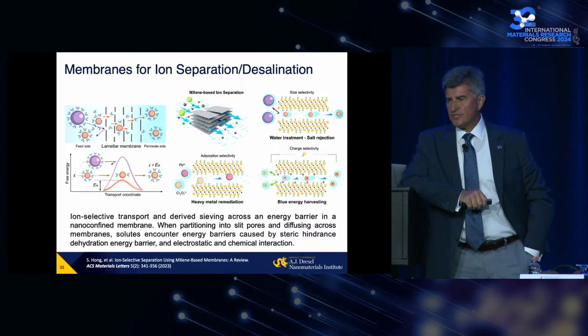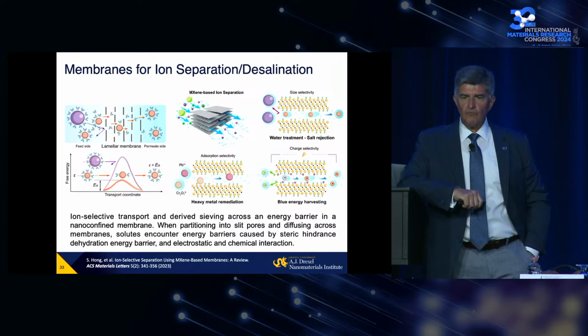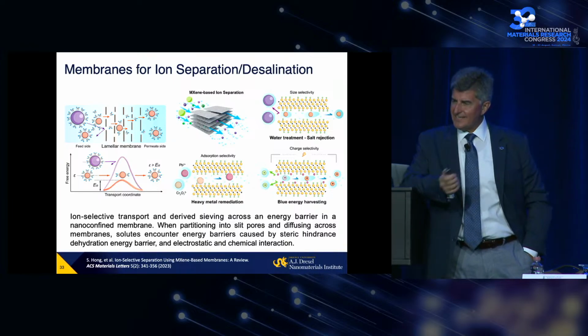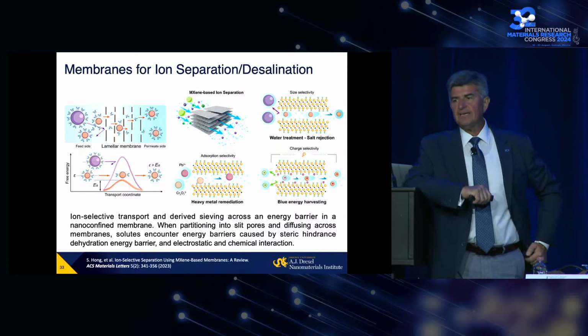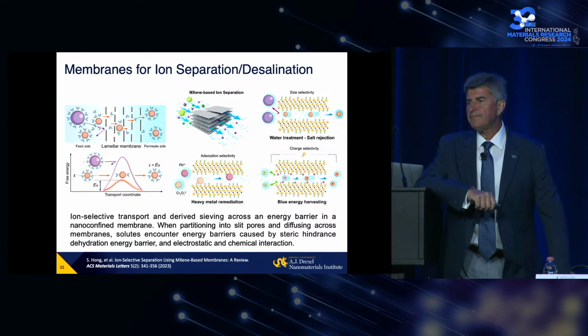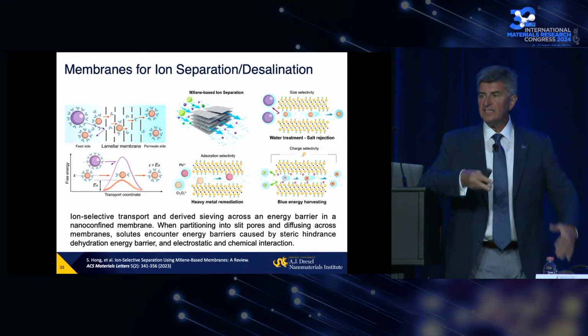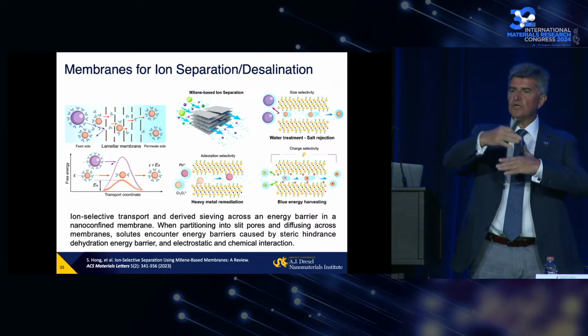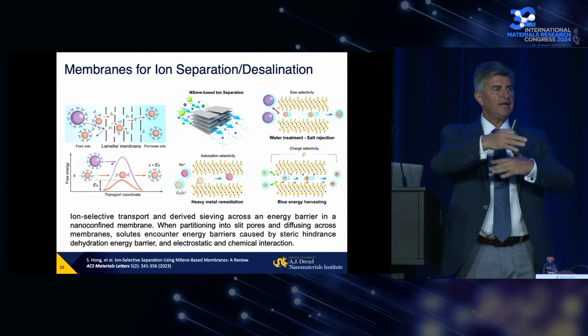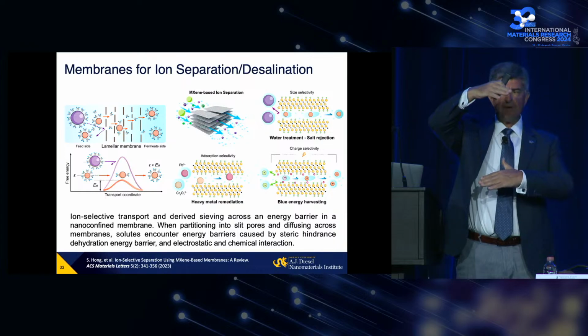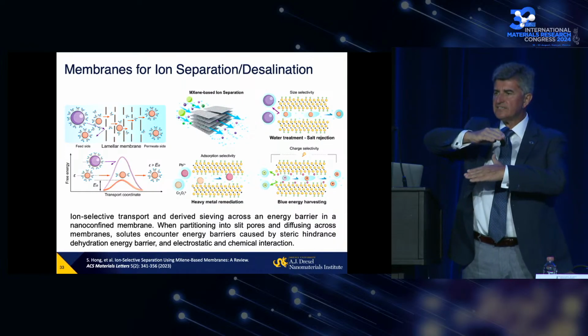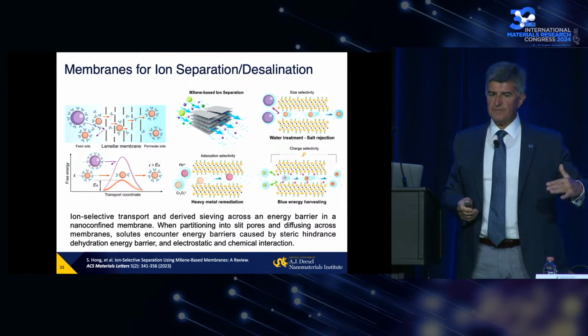Water desalination: there may be more water in Mexico, particularly from rain, at least in some parts, but many countries, the Middle East for example, fully depend on desalination. Whenever you have conducting materials, you can control transport of ions by applying potential. You can control it by adjusting spacing between layers, and by controlling surface chemistry of the material.